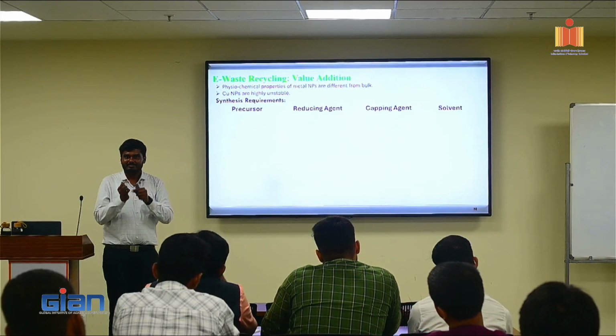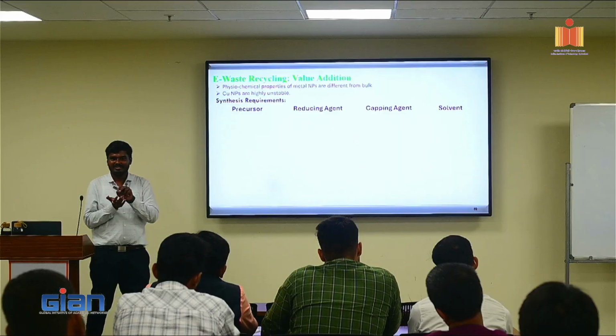So it caps all the nanoparticles. Third one is solvent. Typically people use water. If you use water, copper gets oxidized quickly. So now I had to do lots of literature survey and see what type of solution we have, this copper solution, then reducing agents.